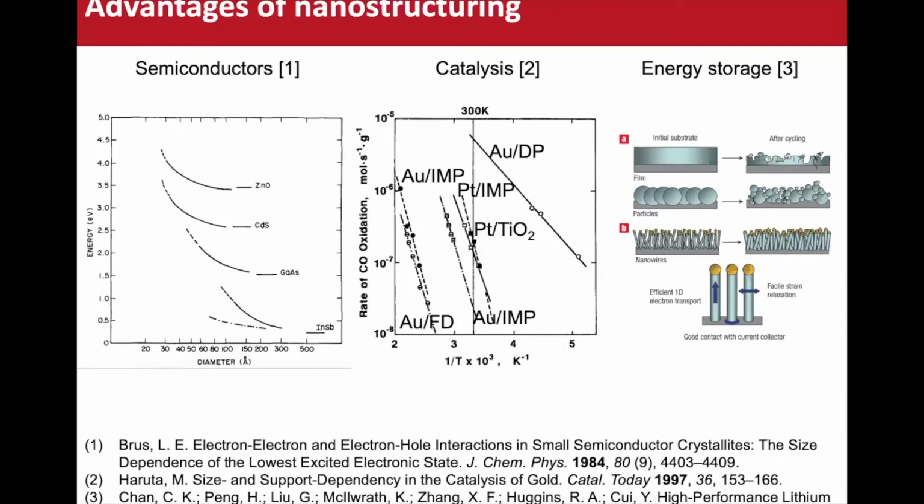For energy storage, there are advantages of nanostructuring silicon anodes in the form of nanowires, as you can see here. You can have high performance in rechargeable lithium-ion batteries, with higher energy capacity versus commercial graphite anodes. This work was published more than 12 years ago. The use of nanowires enabled cyclability and avoided the pulverization problems that one would experience with bulk silicon anodes.